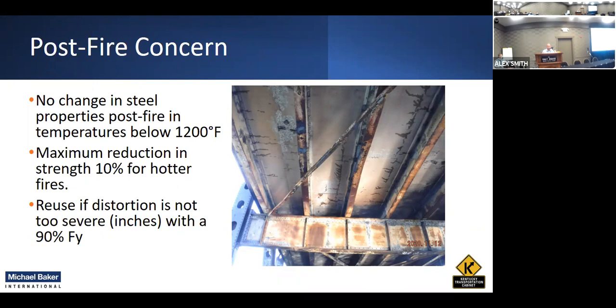After we did our inspection, we did some metallurgy analysis and took those steel core samples. Luckily, we did not see any change in steel properties because of the fire. Looks like it did get below about 1,200 degrees. So that's a maximum reduction in strength of 10% for hotter fires. And then we could reuse it if distortion's not too severe, with 90% of yield strength.